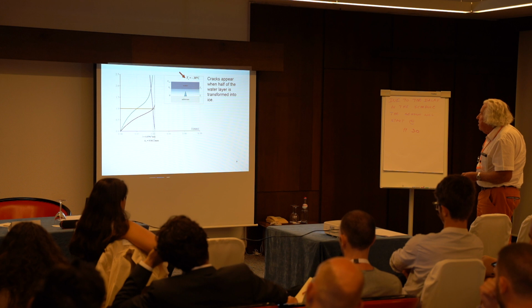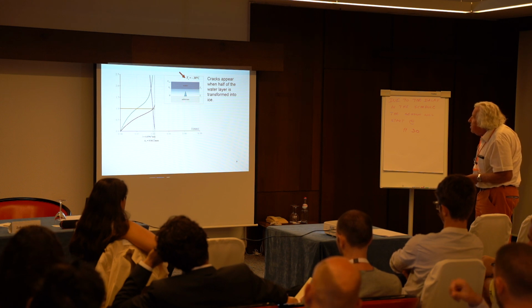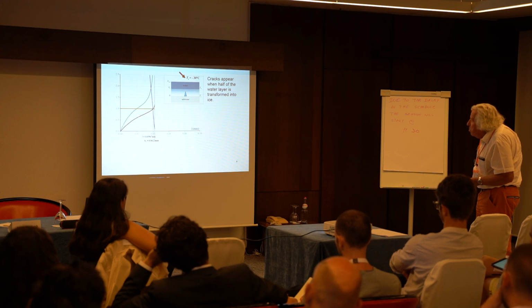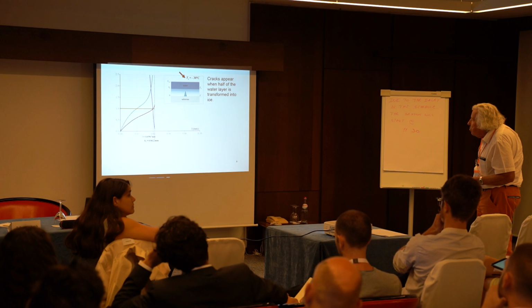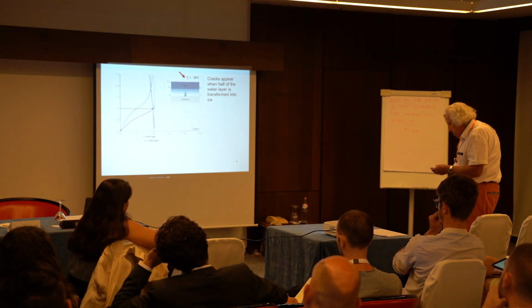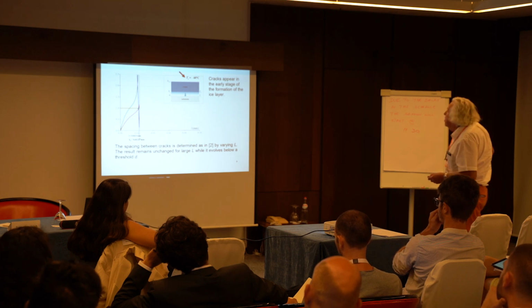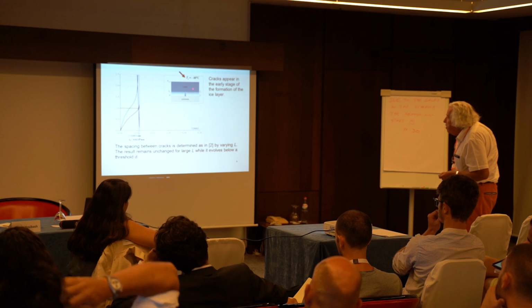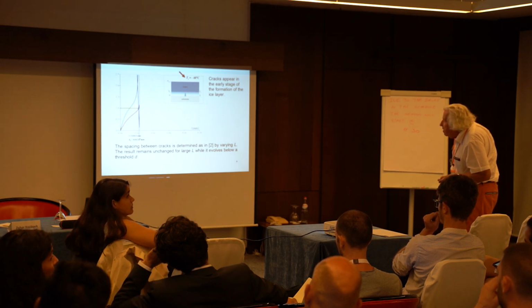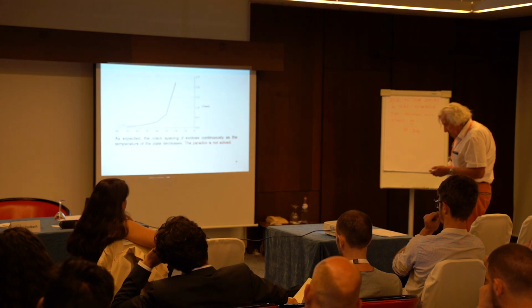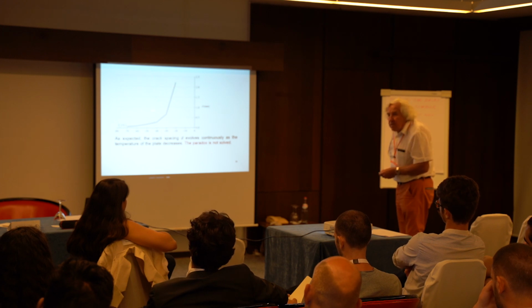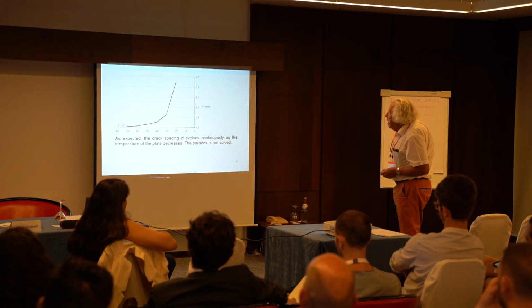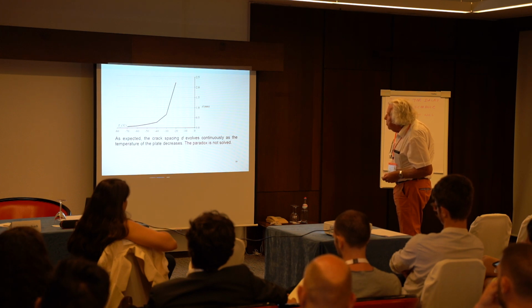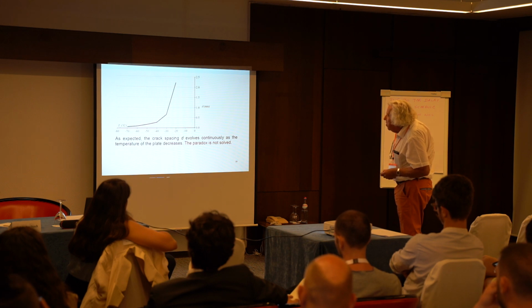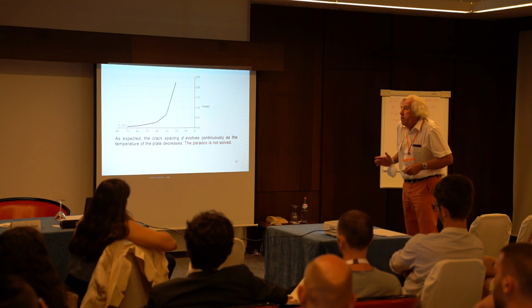Okay? If we consider minus 30 degrees, of course the ice thickness is smaller. And again, the blue line is the stress, this is the energy condition, and we have a solution here, okay? And now if we move to the temperature minus 40, the ice thickness is smaller, but we still have a solution. And finally, if we put that on a plot, what we get, what was expected, is that the distance between cracks during ice formation decreases when the temperature decreases, I mean when the load increases.